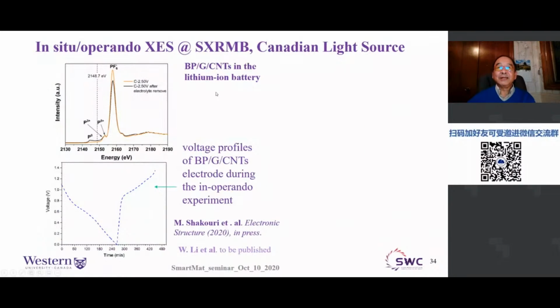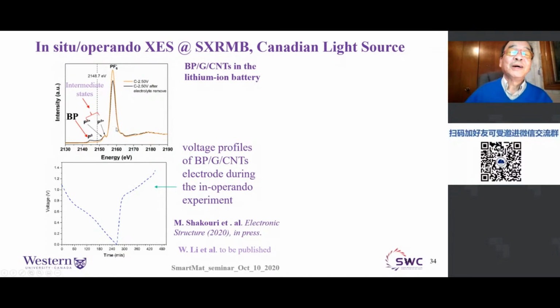Now we do a very quick test of the in situ experiment by using a composite of black phosphorus, graphene, and carbon nanotube in a lithium-ion battery, right? So here is the absorption in the phosphorus K-edge, and you can see the phosphorus 0, which is black phosphorus, and you see some intermediate states, and you see a very strong peak due to the electrolyte. Okay. Now, when we do the emission, this is where the synchrotron comes in. If you tune the excitation to below this high oxidation phosphorus, we excite only here. Then the only thing we are exciting is just the phosphorus 0, because we are interested in how black phosphorus changes during the cycling.